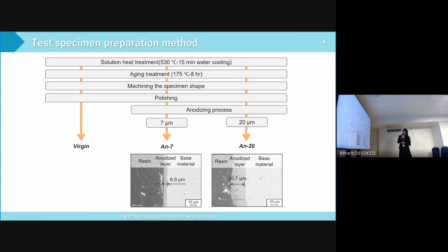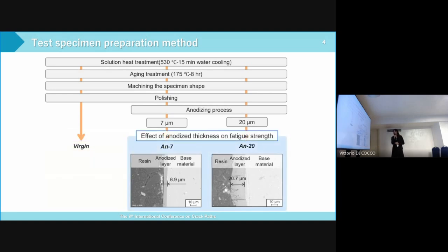Moreover, this is the cross section that was polished and observed by SEM. As a result, the AN7 and the AN20 are forming the target film thickness. Today, I will present the effect of the anodized film on fatigue strength, comparing virgin with AN7, and the effect of anodized thickness on fatigue strength, comparing AN7 with AN20.